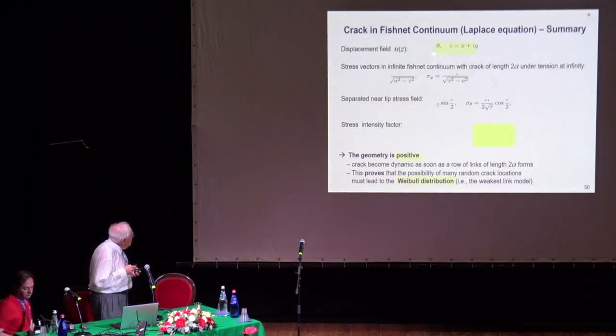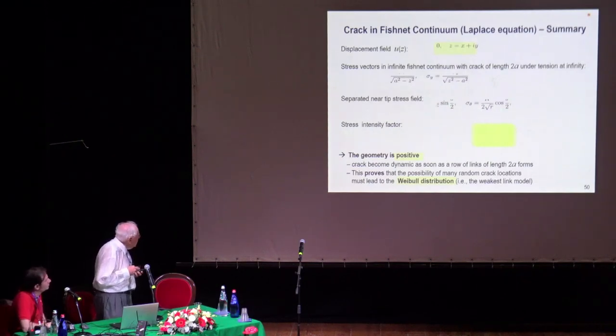Anyway, the exact solution of the Laplace equation is very simple. It was done in complex variables. Displacement doesn't show here. Stress vectors in an infinite fishnet give, again, a complex variable solution. It is a simplified version of the Westergaard solution. This is a complex variable, sigma y, sigma x. It gives a separated stress field. The stress factor disappeared.